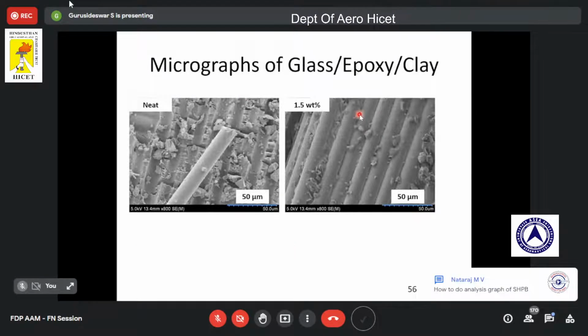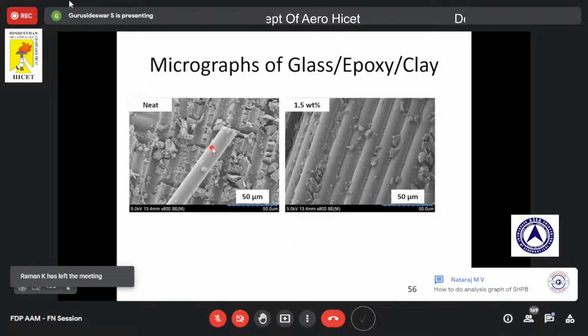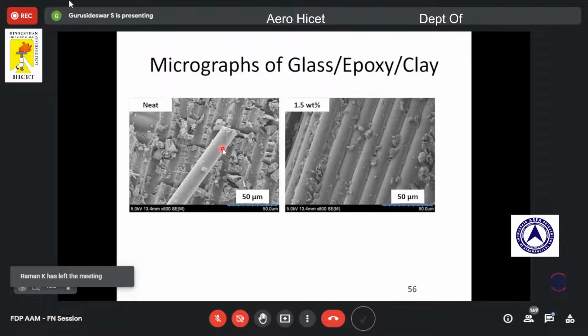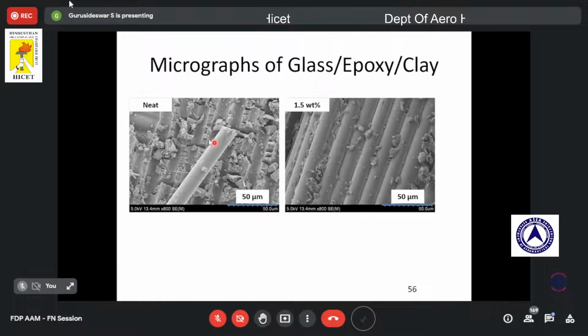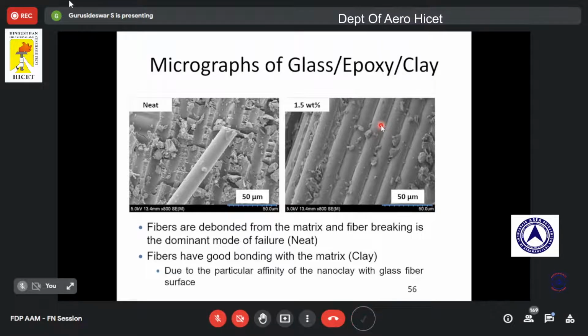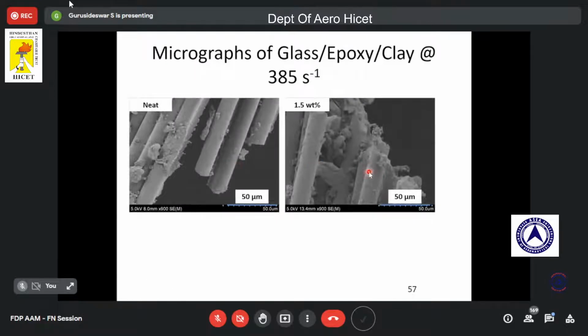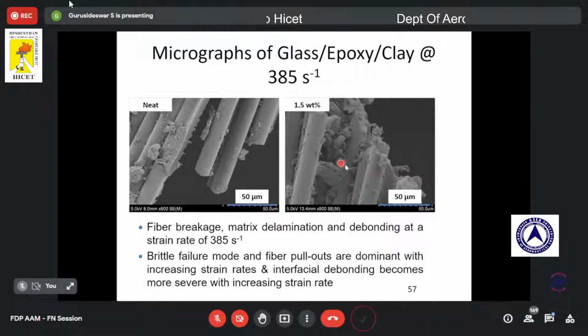Again, this is the figure for glass epoxy clay. You can see poor bonding between matrix and fiber for neat epoxy, but we could see good bonding for clay epoxy samples. Because of clay addition, we were able to get better bonding with the fiber. This is what we can observe from this micrograph. Again, this figure shows fiber breakage and debonding at high strain rates.